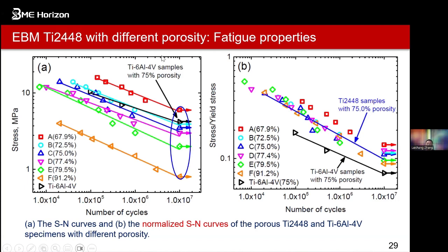We can still see these kinds of structures for the normalized fatigue life. You can see the Ti6Al4V seems to have the better fatigue life, but actually not, because this one is just absolute. In the normalized one, the fatigue stress is divided by the yield stress. You can see the Ti2448 at 75% has a higher fatigue strength compared to the Ti6Al4V for the structures.